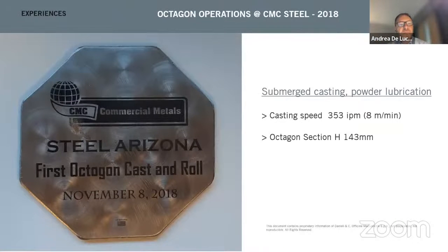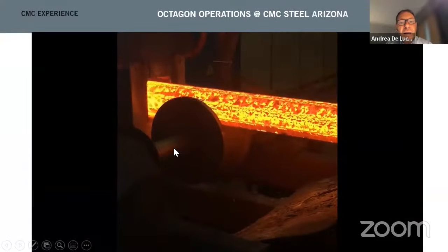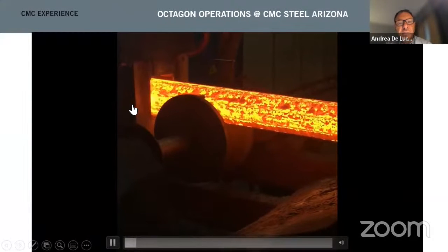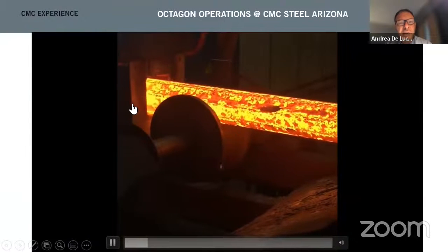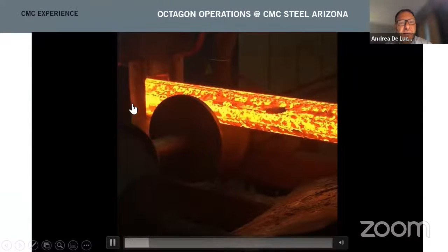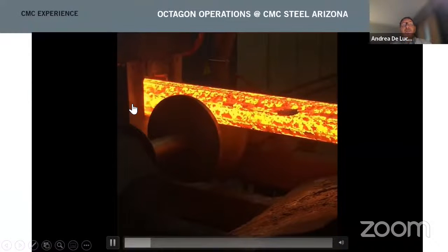But as happened 10 years ago, the first very perfect application was again in CMC Steel Arizona, the first meter. We applied in 2018 the first octagon, and they immediately exceeded the limits of the square, and they cast up to 8 meters per minute, 353 inch per minute. And since that time, they didn't remove it anymore. They have been casting for 4 years now in octagon. You can see this movie is not accelerated. This is the billet outside of the caster at 8 meters per minute.